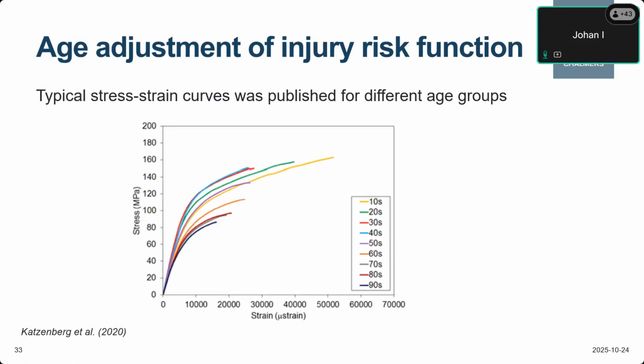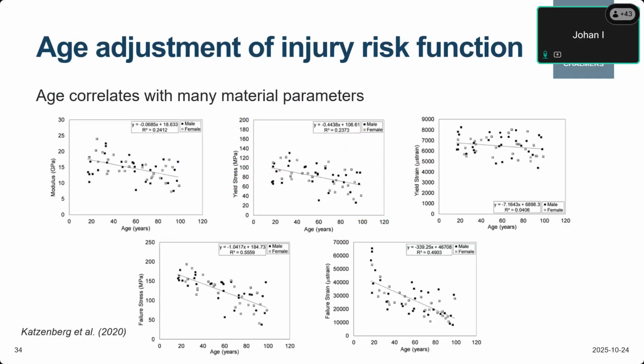The typical stress strain curves were published in Katzenberg here for different age groups, and we can see that we start with the yellow one, teens, then we go to 20 years old and 30 years old. So we can see that the stiffness and strength of the ribs increases, and then from 40 years old it starts to drop down to 90 years old. We can see that the yield surface moves up and then moves down. Another thing we can see is that for each decade the ultimate strain decreases. We can also plot this in this form, which was done in Katzenberg.